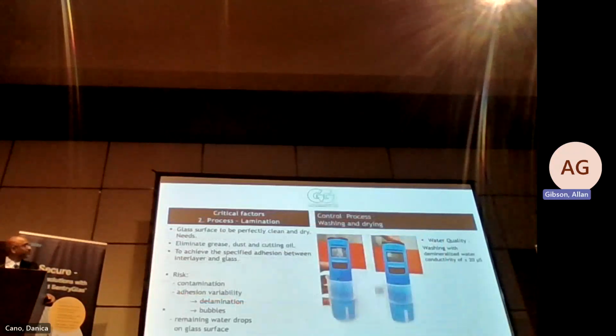And so there comes a challenge for PVB manufacturers when you're putting glass on the external facade, which is to use high adhesion PVBs. And nobody talks about it because it's not there. So anybody can use a low adhesion PVB and then after 5 years you get delaminations. So this is critical because it is chemistry, it is what it is. For coated glass, you cannot laminate on the air side. So you have adhesion promoters. So those work. Next slide, please.